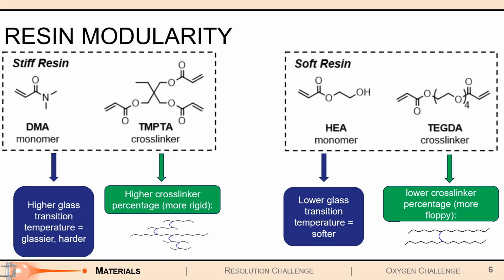These photoredox catalysts are also very good and can be used in a variety of different resins. For one, if you wanted to print out a really hard and stiff object, you could put your photoredox catalyst system into this system on the far left made out of DMA and TMPTA and get a hard, stiff print. If you wanted something softer and stretchier, you could put your photoredox catalyst into a softer resin made up of these monomers to the right, this HEA and this TEGDA. That allows you to print out something a lot softer and stretchier. However, it's not quite as simple as just putting your photoredox catalyst into your monomer resins and letting them go.